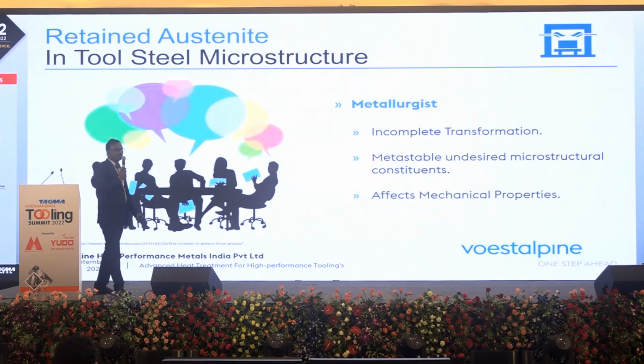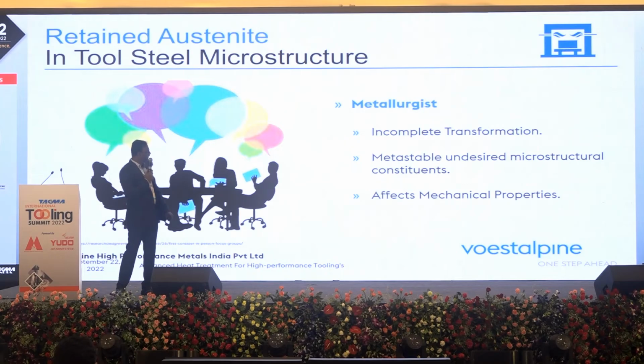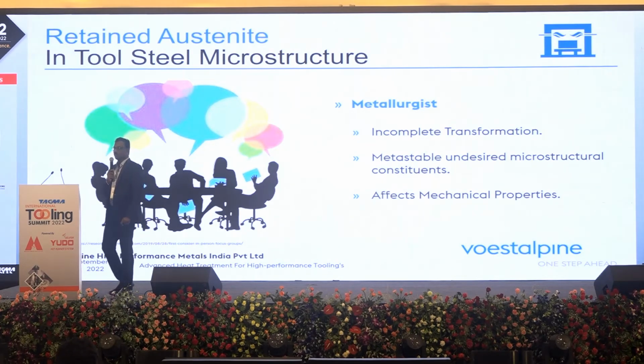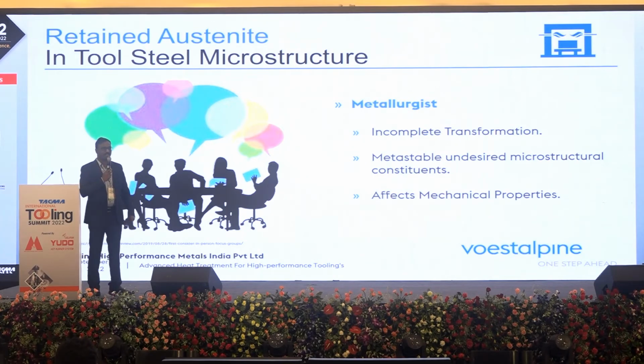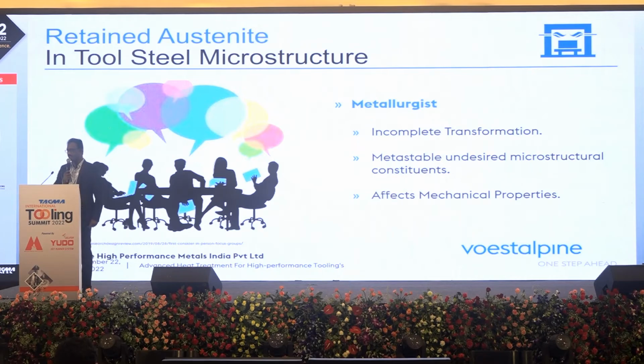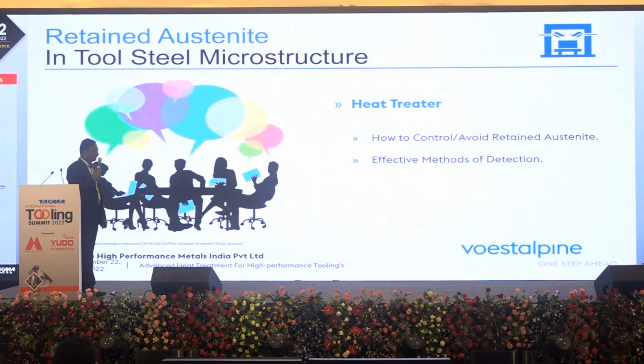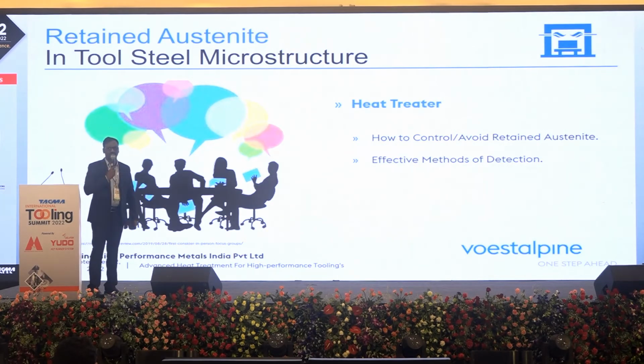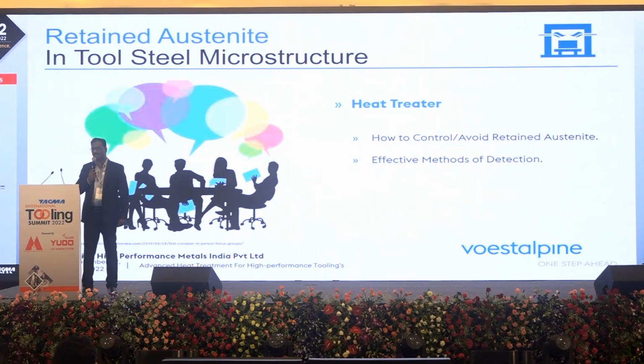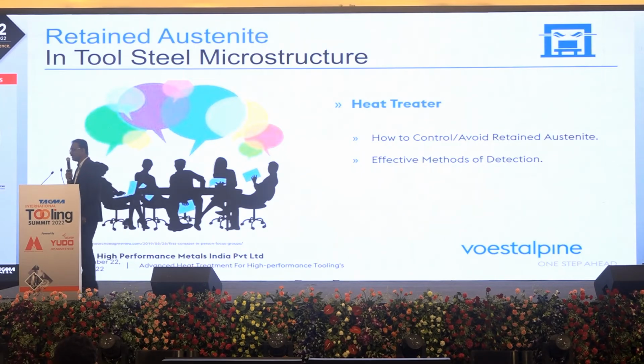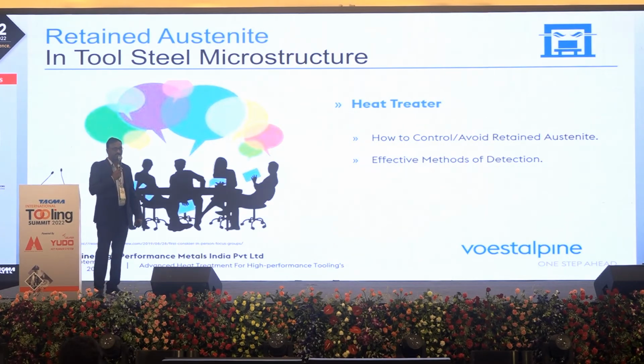What will the metallurgist think in their own way? They say it is an incomplete transformation. There is 10% retained austenite that stayed back. I couldn't convert it, and this is a metastable, unstable retained austenite with multifarious effects. Of course, that affects mechanical properties. Finally it comes to the heat treater. The metallurgist says something, the tooling fraternity says something: that the tool may fail because of heat treatment, having a detection of 5% retained austenite in your tool steel. Then the heat treater will be in trouble.